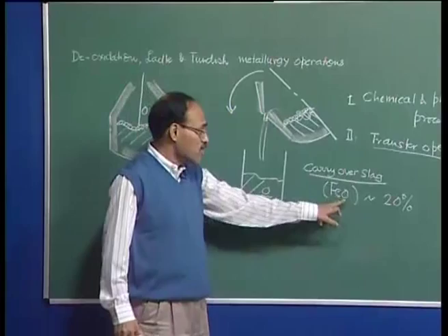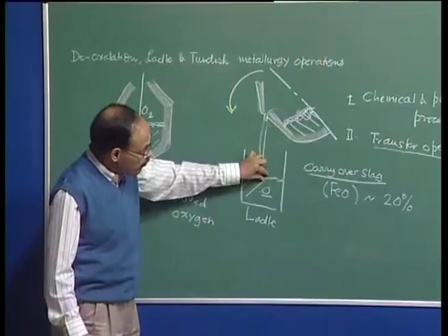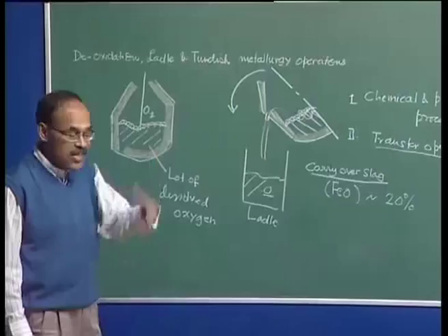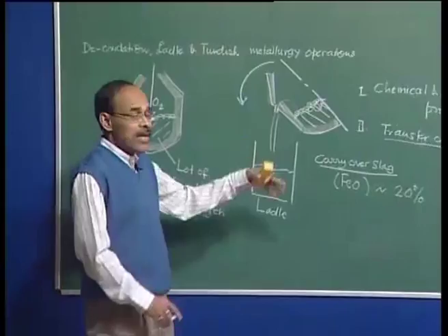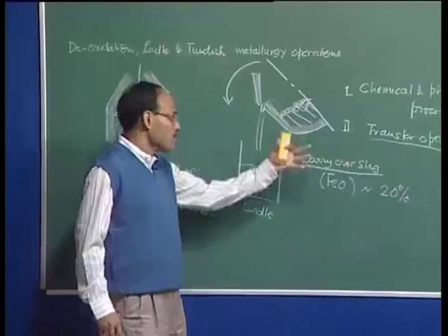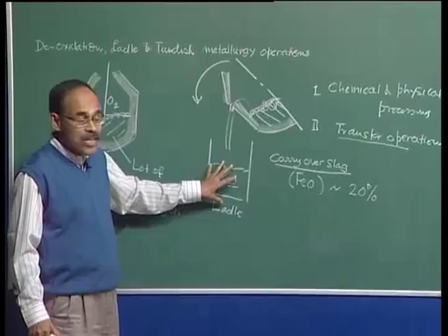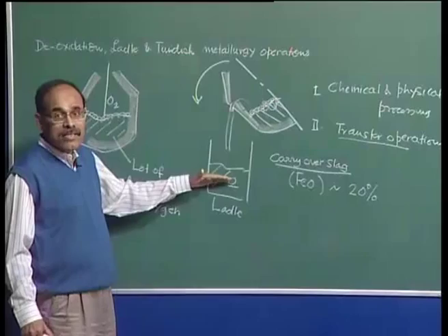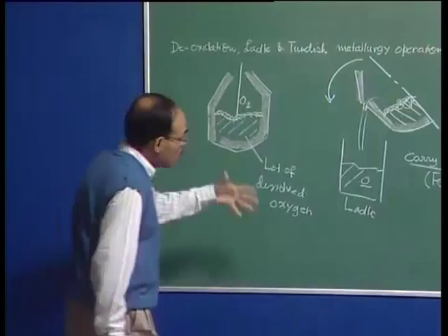We are not going to entertain any amount of this slag coming here, because we are now going to remove oxygen, which is essentially a deoxidation or reducing operation itself. So, the carryover slag, as we advance, we will see, influences adversely the properties of the steel. As a result, all subsequent refining reactions beyond the primary steel making vessels, which are going to be carried out in a ladle, are actually going to be carried out in the presence of a new slag.